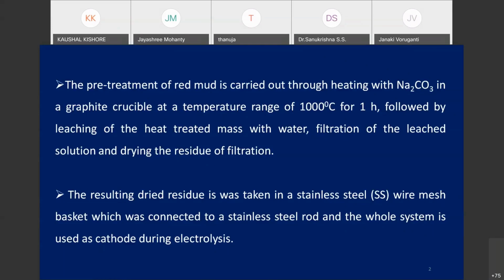During heat treatment with the sodium carbonate, it is found that some metallization actually happened. Red mud contains iron oxide, aluminum oxide, and some part of titanium oxide. But after heat treating, it was found that some part is metallized, and that is a good thing. As I have already told you, in the electrolysis process we usually prepare a conducting material. If you take a conducting source material, then a better electrolysis will happen. That is one of the most important concepts behind why I am treating the red mud before electrolysis. Another part is that any silicon or aluminum can be removed as sodium silicate or sodium aluminate by heat treatment with sodium carbonate and after water leaching. So all this material will be removed.